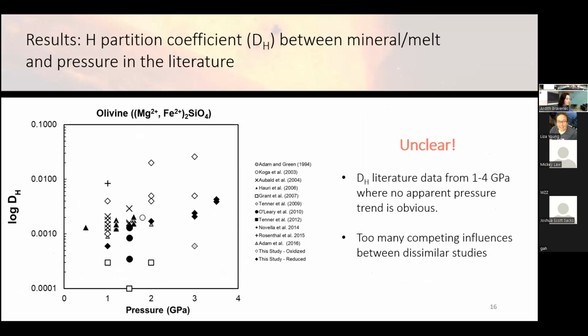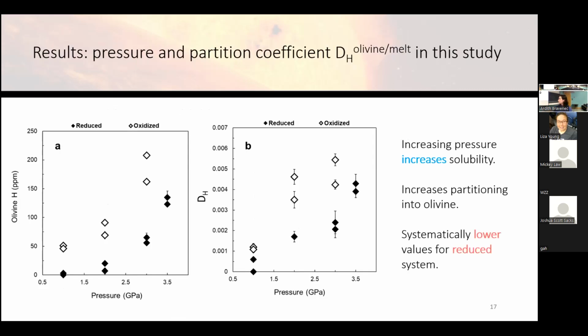But the interesting thing to note here is that there still aren't very apparent trends when you're looking just for pressure effects, which clues you into the idea that there's probably many different competing factors, whether it's temperature, composition, redox, how these experiments were run, and some other parameter people haven't accounted for. So that's why it's important for me to elucidate pressure effects within my own samples, even if it's been studied before. And indeed, when you isolate one variable, you can clearly see that there is a positive effect on solubility with pressure, where both for the reduced samples given by those black markers and the oxidized samples given by the white markers, we see that as you increase pressure, as you go deeper into a planetary interior, you increase the solubility of hydrogen, and that is bulk hydrogen, into olivine.